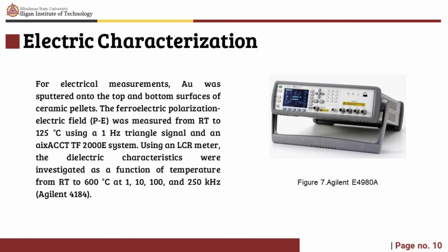For electrical measurements, Au was sputtered onto the top and bottom surface of ceramic pellets. The ferroelectric polarization's electric field was measured from room temperature to 125 degrees Celsius using a 1 Hz triangle signal with an AIX ACCT TF 2000E system. Using an LCR meter, the dielectric characteristics were investigated as a function of temperature from room temperature to 600 degrees Celsius at 1, 10, 100, and 250 kHz.